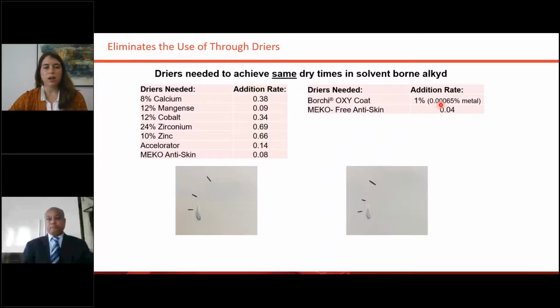Another thing to note is commonly on resin solids, this is the addition rate as supplied on resin solids, but many times the standard cobalt level is around 0.06% cobalt metal in your alkyd paint. With Borchi OXY Coat, it is used as supplied, but it has a very, very low activity rate of the metal ligand technology. So taking into account that ligand, and then even lower amount of actual metal, you're only adding at a 1% addition rate.